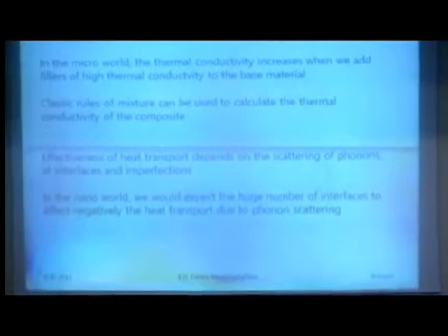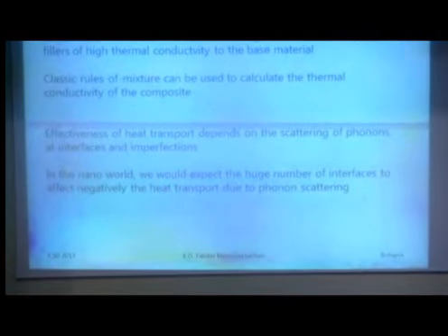We can easily calculate the thermal conductivity of the composite by classic rules of mixture. No big science there. However, we know that the effectiveness of heat transport depends very much on the amount of scattering of phonons, let's say the heat carriers, at interfaces and at imperfections. So in the nano world, we would expect a huge number of interfaces to affect it.